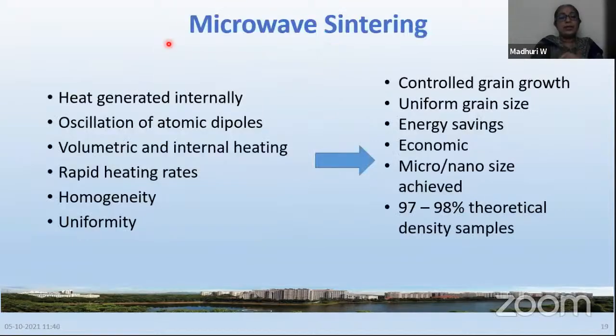You can see here, the heat is generated internally. Oscillations of atomic dipoles generate friction, which generates the heat inside, and there will be rapid heating rates. When compared to 16 to 18 hours or a few days of heating, this is only happening in half an hour. Half an hour to 40 minutes is a very short interval of time. It's the time of your regular class. So it doesn't need much time, and it will not use more electrical energy either. You are also saving energy. You are saving your time.